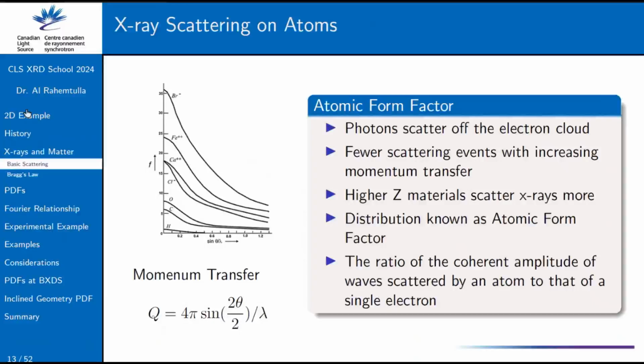And what that also means is that different ions, or if you still have the same charge but different elements that have ions, you can still have sort of the same principal scattering power. But what we see is that as you go off of zero angle and start going to higher scattering angles or higher momentum transfer, there's going to be a fall off. And that fall off is dictated by the orbital structure of the atom, of where those electrons lie.